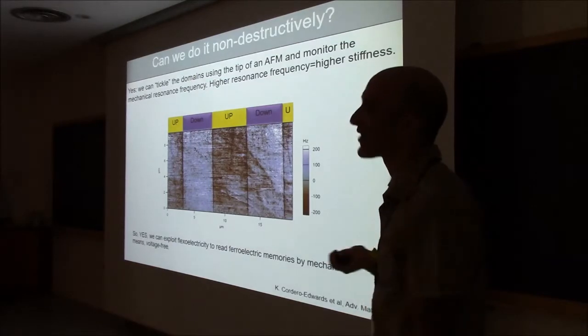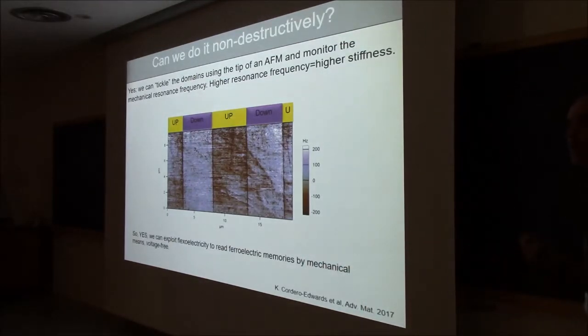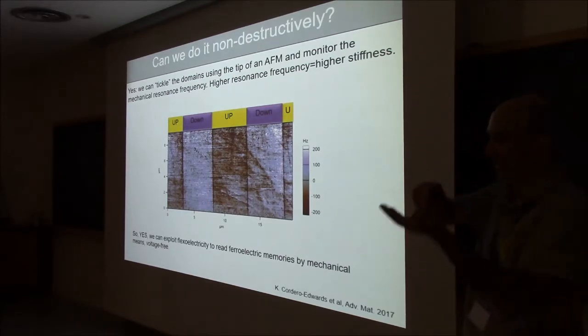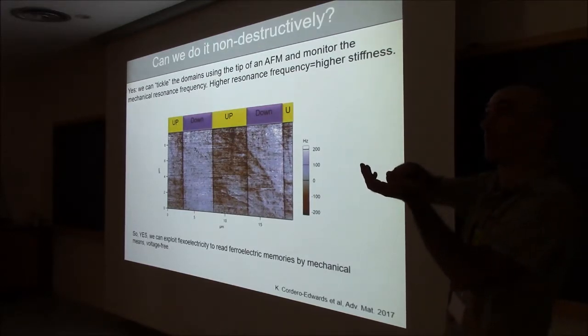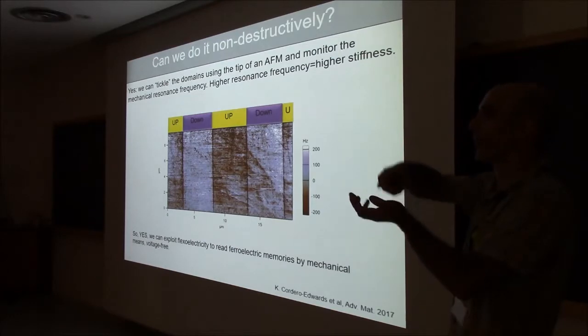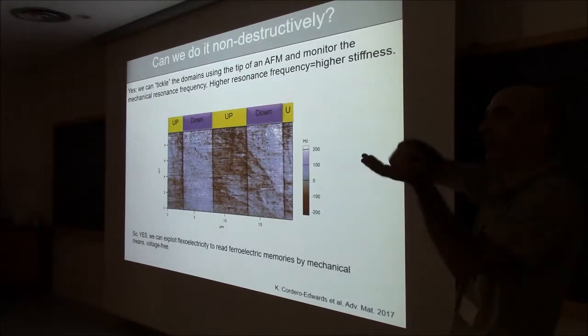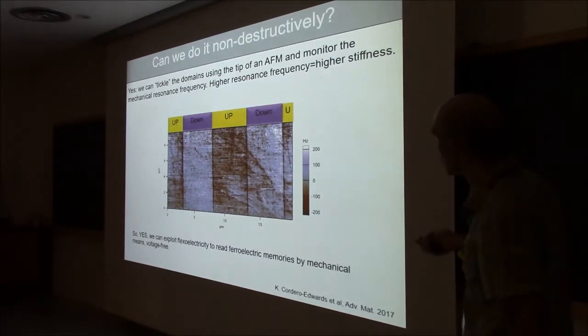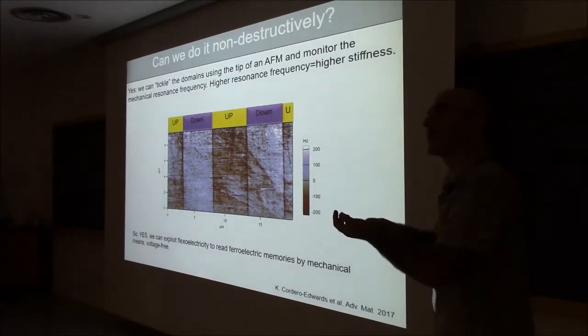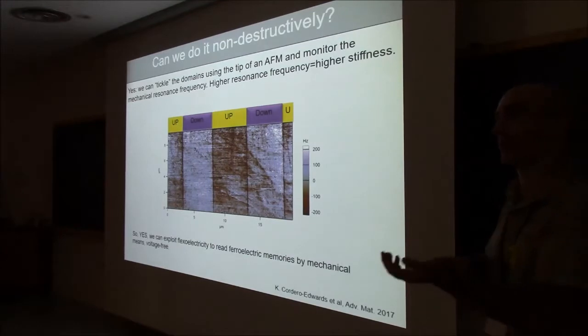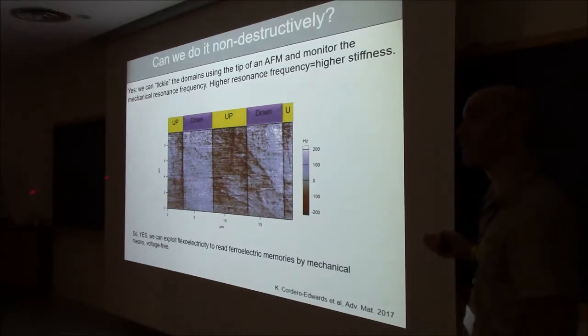Okay, but the stiffness is actually an elastic property, so we should be able to probe it without making holes, and we can do that by tickling the surface with the tip of an AFM. So you look for the resonance frequency of the AFM in contact with the surface, and depending on whether the polarization is up or down, you see a bigger resonance frequency or a smaller resonance frequency. The difference is not very big, but it's there.